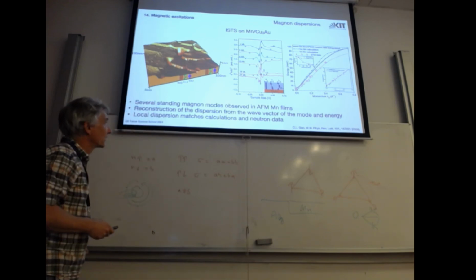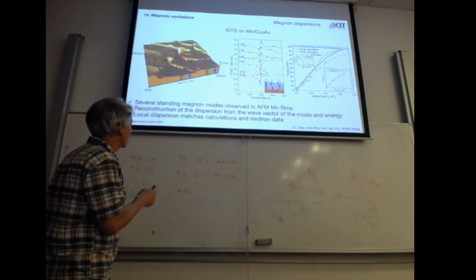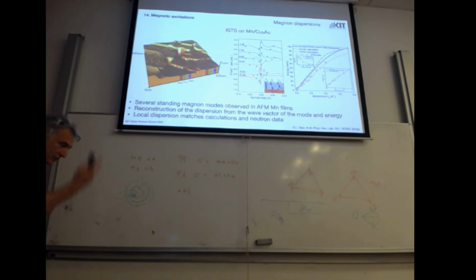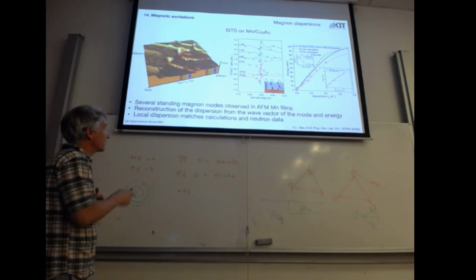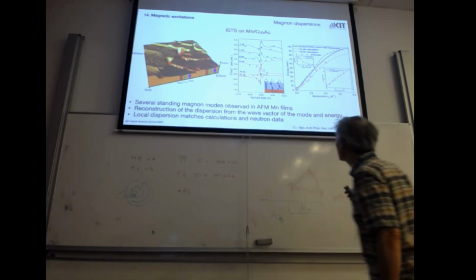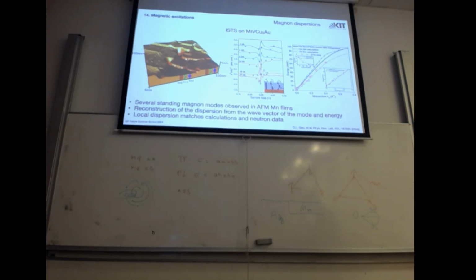If we change the thickness, the k vector changes here in a superposition of plus k and minus k states traveling in the z direction. So just by counting this n, we can reconstruct the q vector of the magnon, and we have done it here. So this is the momentum, this is the energy. So I take now this energy as a function of momentum that I reconstructed from the standing magnon condition. And the dotted line is an ab initio calculation for magnons in the system. You see it matches perfectly our observation.